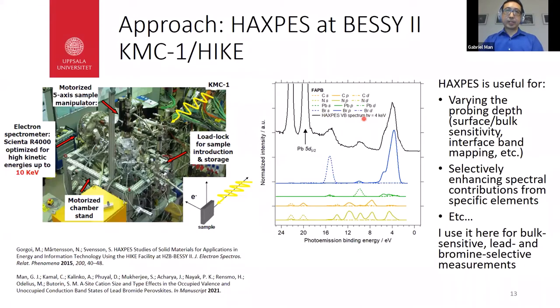This is where we've done the HAXPES work. This is the beamline KMC-1 and the end station HIKE at BESSY II. So HAXPES is quite helpful for many things, such as varying the probing depth and doing interface band mapping. Here, I've exploited the ability of HAXPES to sort of selectively enhance spectral contributions. So here is a spectrum acquired from formamidinium lead bromide at 4 keV. And the states that you see here are mostly from the blue, bromine states, and the green, which is lead states. So you don't really see the contributions from carbon and nitrogen. So it really allows us to focus just on the lead and bromine states.